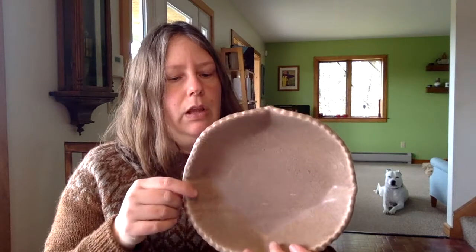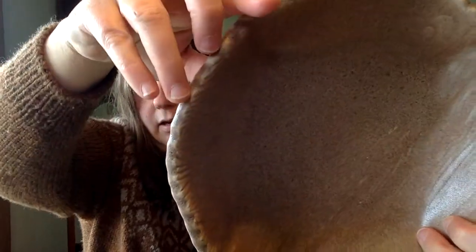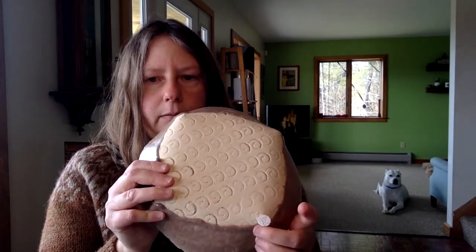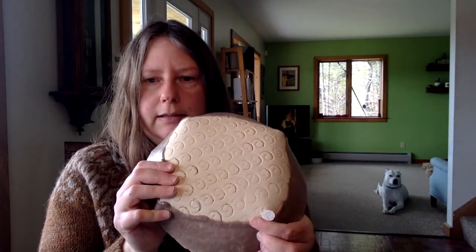These shiny ones were kind of house glazes for the whole studio. My instructor gave me a brown wood glaze for the largest vessel, but it was mixed to a different thickness and I didn't realize that, so it's pretty heavy. You can even see close up — there's pitting that happens when the glaze is so thick that it's kind of just boiling in the kiln, getting bubbles, and then those bubbles pop and you end up with this pitted look. The glaze was too thick and pooling up, running down the sides while being fired. It was so thick on the outside it ran over and actually fused onto the kiln — so I'm going to need a rotary cutter power tool to grind it down and make it smooth.